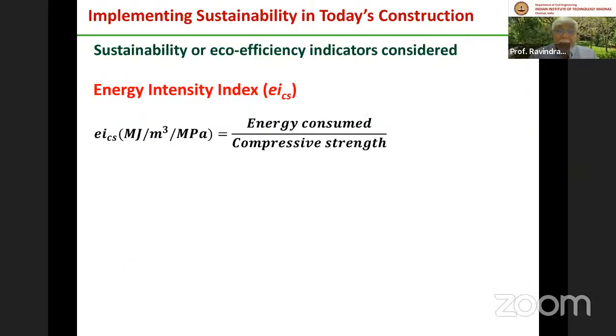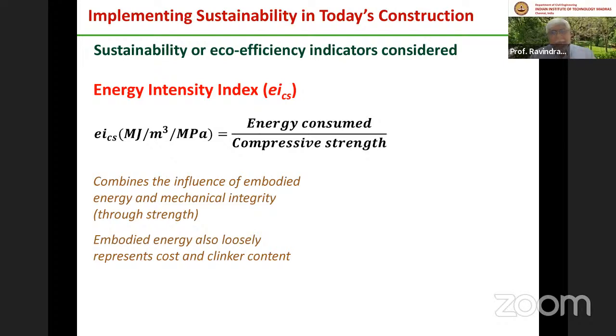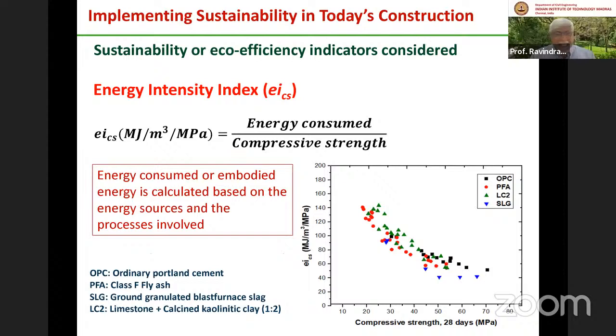So let me go on to bring in durability also. When we are talking about sustainability, I said that durability and other parameters are important. So we are considering two types of indicators. One is the energy intensity index, which combines the effect of energy and mechanical integrity. And you can see that it also reflects well the improvement in the structural level that we will see when compressive strength increases. If we look at only the energy, it looks as if a higher grade concrete requires more energy and will have more emissions. So that is why we have divided by the compressive strength. So you see here that the energy intensity index decreases as we increase strength because the efficiency becomes better.